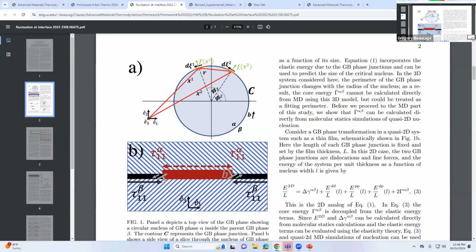All right, so you have a high energy interface. A lot of times high energy phases, crystallographic phases, tend to form because, if you have a liquid going to crystal, the high energy crystal is closer in energy to liquid than the low energy crystal. So it's easier for it to jump from liquid to the high energy crystal, and then you get a crystal transition to the low energy crystal. So you have 2 nucleation events. One is the high energy, like the beta phase forming in a liquid. And then afterwards, after annealing, the alpha phase would appear within the beta phase to reach the equilibrium lowest energy state. Right. So that's the general idea he's doing here also with this interfacial problem.